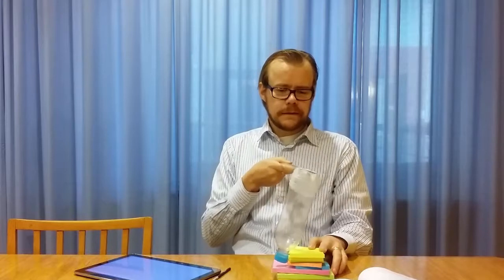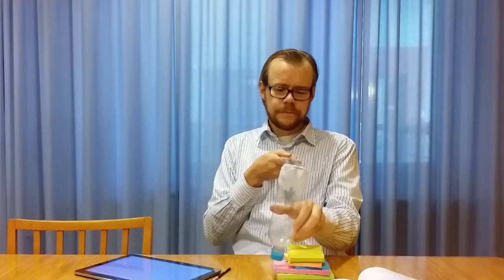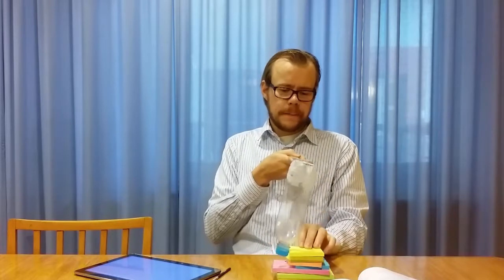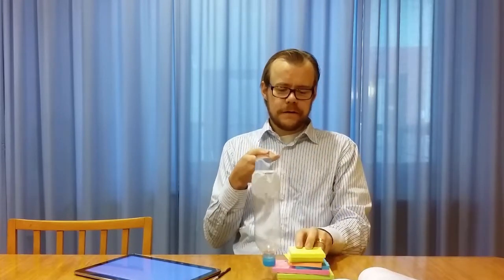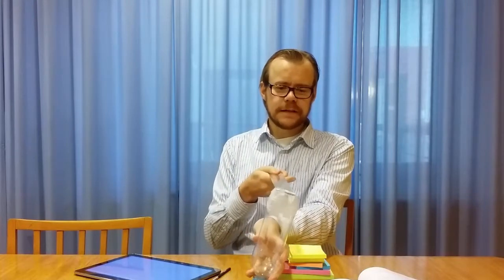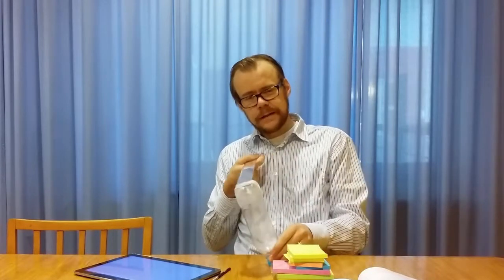And here it scans and then I come to the object, and then the tip will bend like this a little, so it will have some kind of torsion motion here. And then when it comes over it snaps back and goes back down. And this is very clearly seen if the sample is sticky and not very hard. Then the tip will have these friction forces against the surface while it scans.